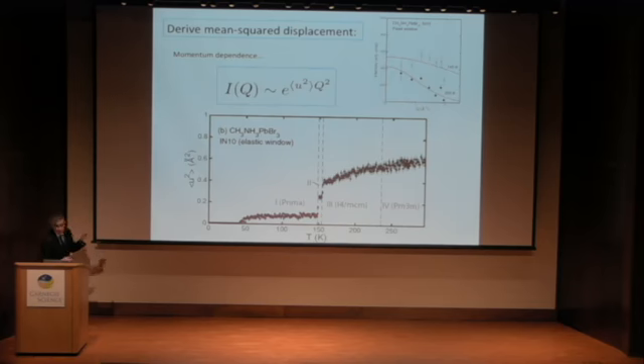Again, this is the mean squared displacement based on the time window of the instrument. So you have to think about the fact that on top of this, there's an energy resolution of about 1 microeV. If you plot that mean squared displacement as a function of temperature, you see that something enters into the time window of the instrument at around 50 Kelvin. Then there's a big jump when you go into the tetragonal phase. Interestingly enough, there's nothing clearly observable when you go from the tetragonal up to the cubic phase.